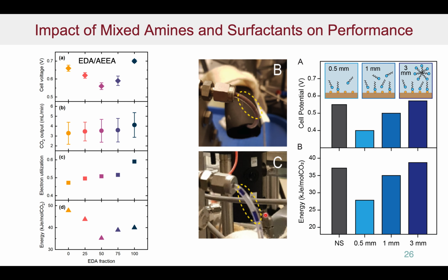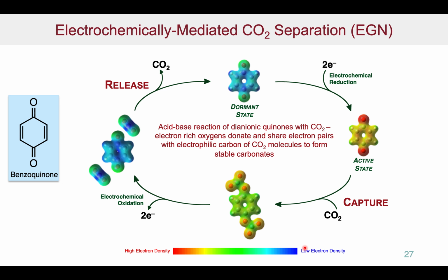And this can lead us to really clean, separated solutions of the gas and the amine solution, the copper amine solution, as shown here. This has led again to a significant reduction in the overall cell voltage and also in the energetics of the system. So we're down to, in this particular case, about 27 kilojoules per mole, which is quite significantly lower than what you had before. So this shows there are some very strong indications that we can do a great job on improving performance.